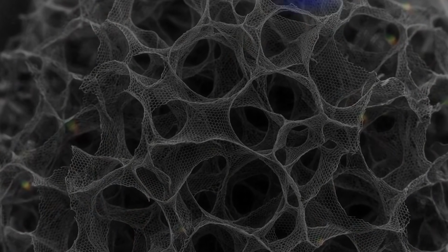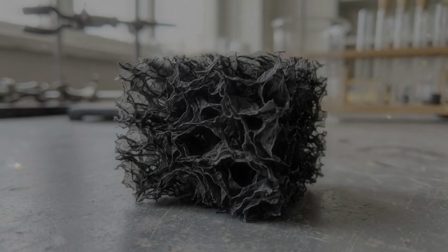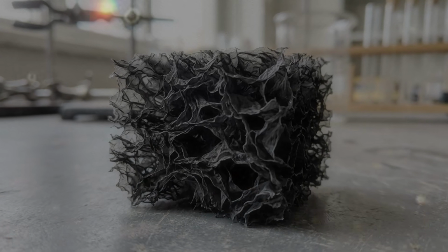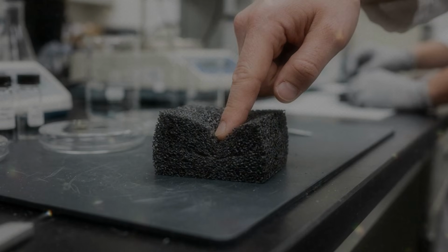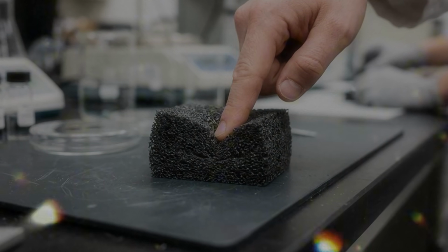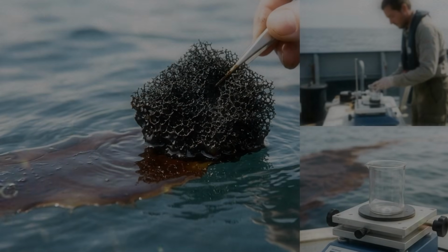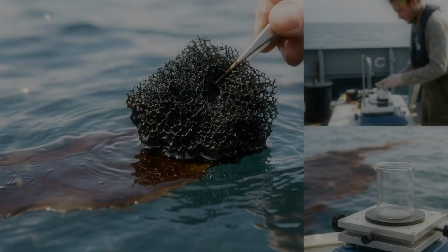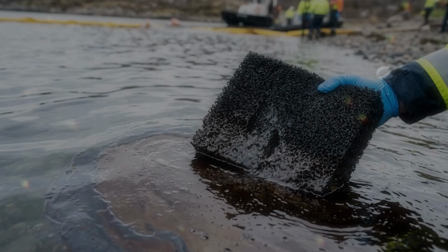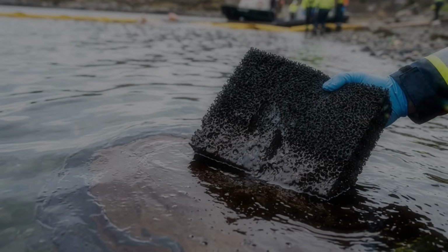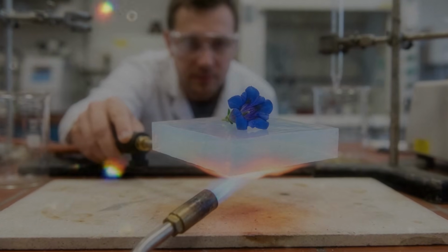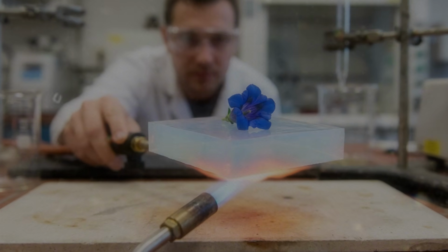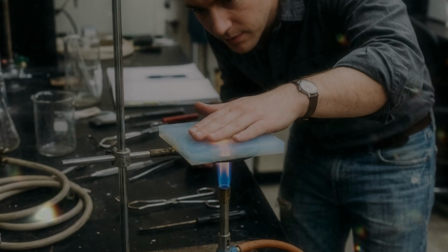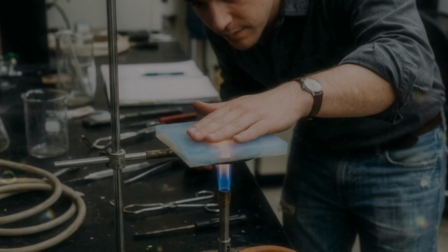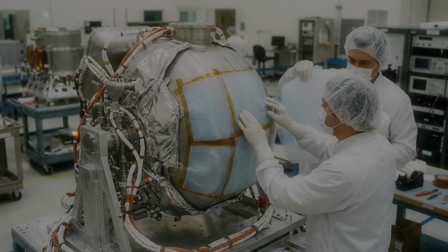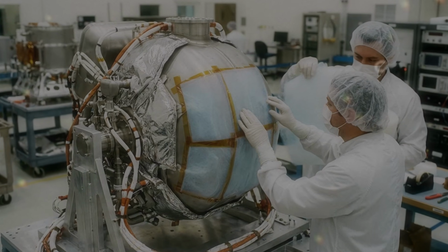A sensor of this kind can detect a finger tap, movement in a joint, vibration from a machine, or pressure beneath a soft surface. Because the aerogel weighs very little, it can be added to clothing or flexible equipment without creating much extra load. Sensitivity alone is not enough. The signal must remain stable. The material must return to the same state after each use. If the sheets slowly stick together, the resistance may drift. If cracks form, electrical paths may disappear permanently. Temperature can also alter conductivity. Moisture may enter the pores and change the contacts. Oils from skin can coat the surface. A useful sensor requires protection, calibration, and a design that separates the desired signal from all the unwanted changes.